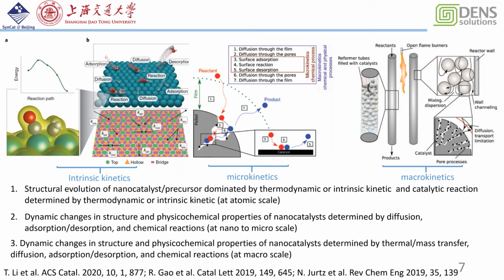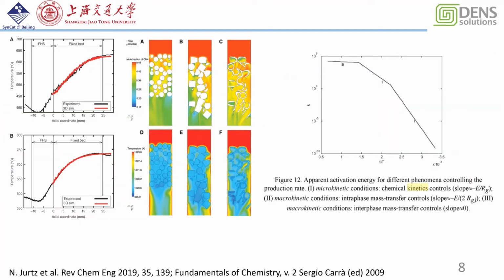But here we want to distinguish the macrokinetics and the intrinsic kinetics, because when I use in-situ TEM, I found that even by using a catalyst with several hundred nanometers, which is very different from the fixed bed reactor, we also have a very different kinetic problem from the intrinsic kinetics. So I want to separate these three things and explain how the macrokinetics dominates the catalytic reaction happening inside the in-situ holder, strongly manipulates the performance, and gives a very complicated chemical view behind the reaction. Here we give an example of why the fixed bed reactor is not so reliable.